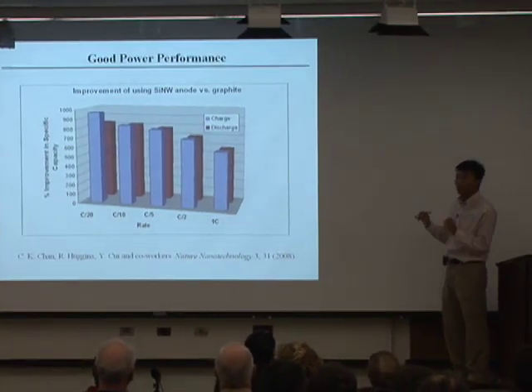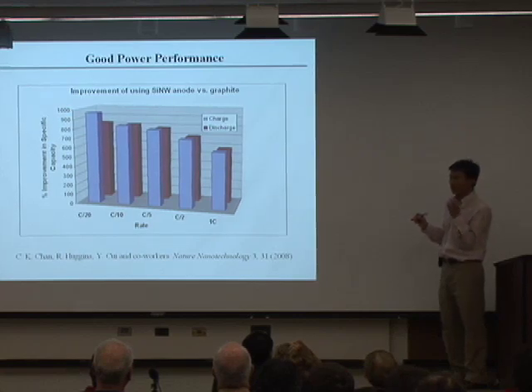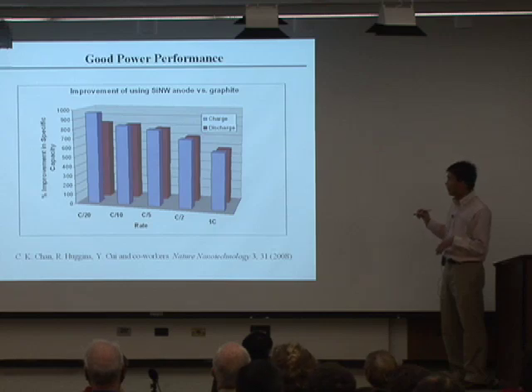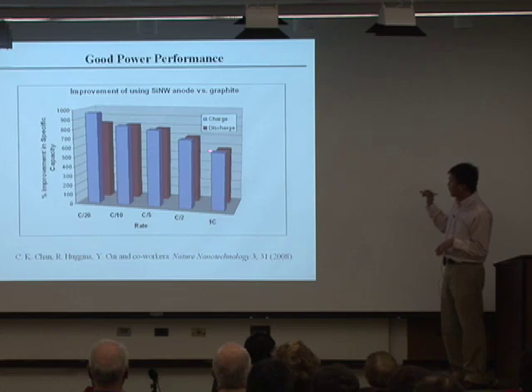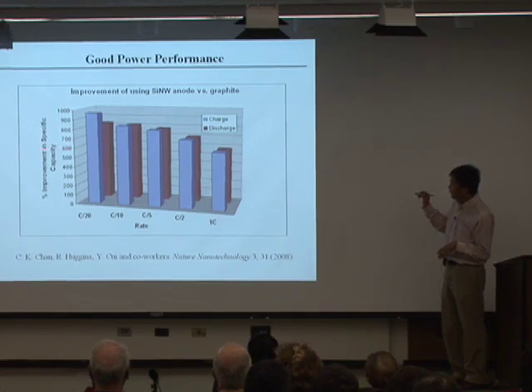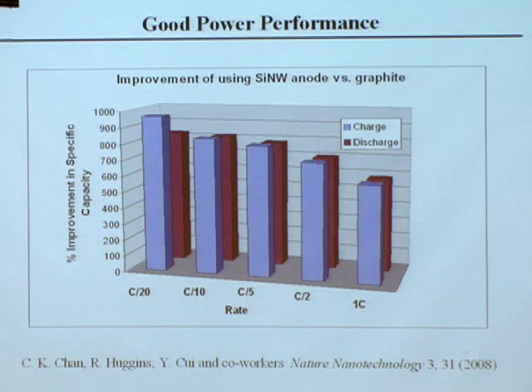Now the question you ask is, using this nanowire, whether you can produce high enough power density, high enough current density to power your iPhone, for example. So we have done the rate dependence of charging, discharging, C/20 right here. This is the battery terminology, meaning 20 hours charging and discharging. And 1C is 1 hour. At the 1 hour charging, discharging, this is the percentage advantage over carbon. You can still have the capacity 500% more than carbon. That's very exciting. And at 1C right around here, you are really approaching the current density that allows you to do your laptop and cell phone charging, discharging.